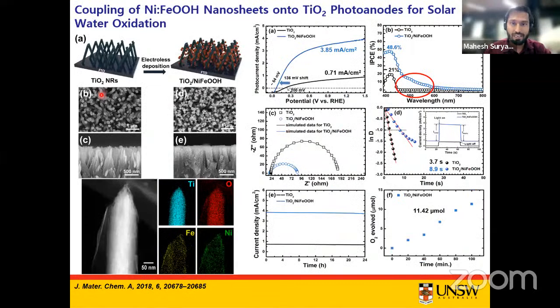these TiO2 nanorod arrays. So these are the basic characterizations. In the SEM, you can see there is a formation of the core shell nanosheet and nanorod heterostructures, which was again confirmed using this elemental mapping. So you can see there is an ultra thin layer of these nanosheets of the NiFeOOH on the TiO2 nanorod arrays, which has covered all the TiO2 nanorod arrays.